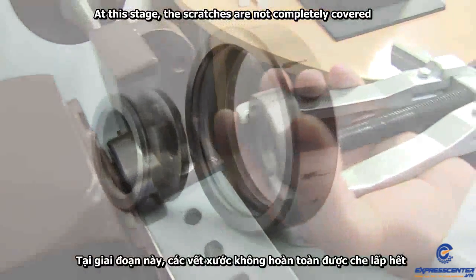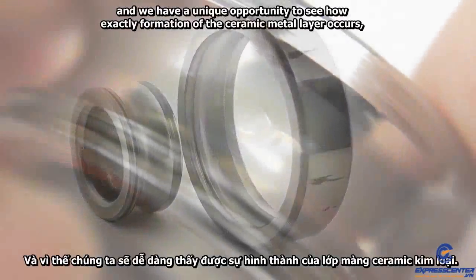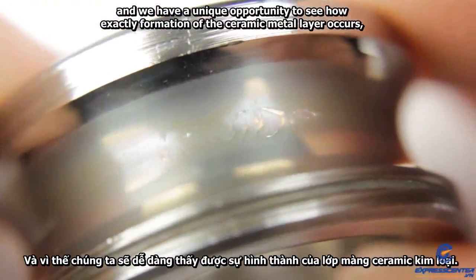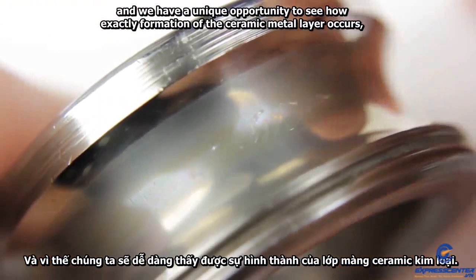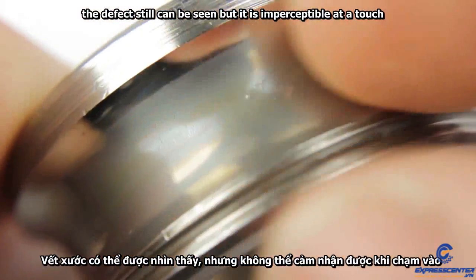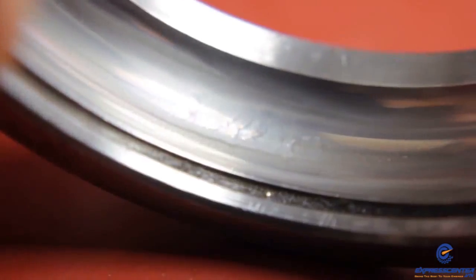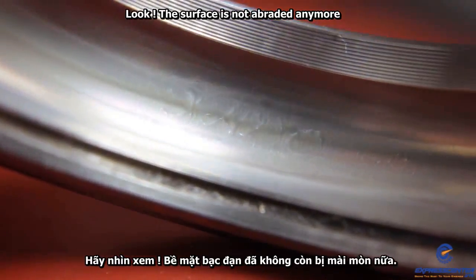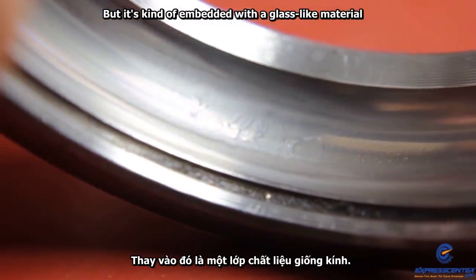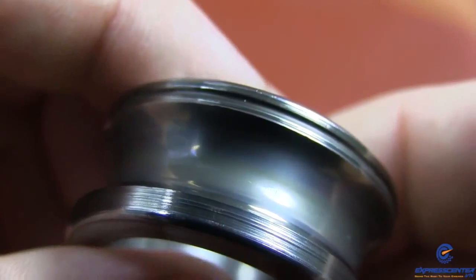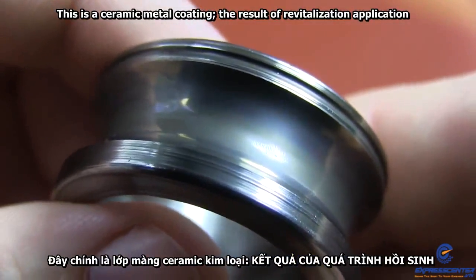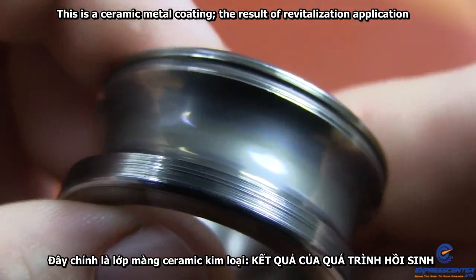At this stage, the scratches are not completely covered, and we have a unique opportunity to see how exactly formation of the ceramic metal layer occurs. The defect still can be seen, but it is imperceptible at a touch. Look, the surface is not abraded anymore, but is kind of embedded with a glass-like material. This is a ceramic metal coating, the result of REVITALIZANT application.